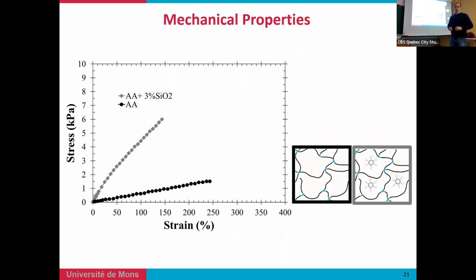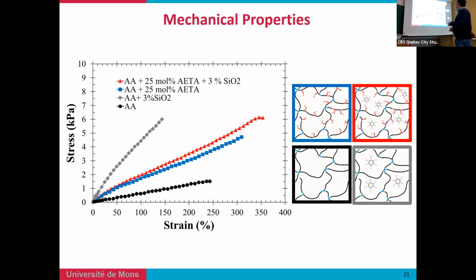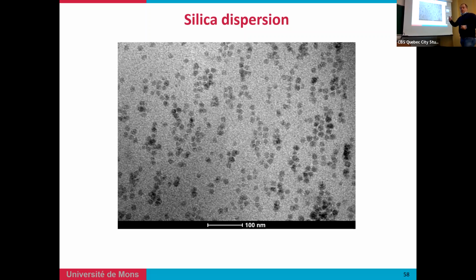Of course, the idea is to have soft matter that is also deformable. This is an example with acrylamide containing 3%, or in its absence, where you can see the stiffness improvement. But in the case of the combination of the ammonium comonomer with the silica particle, you can create a certain supramolecular network that sustains good deformation.